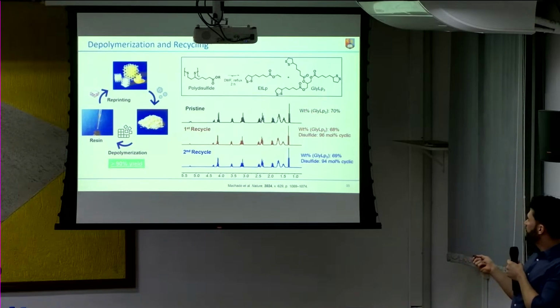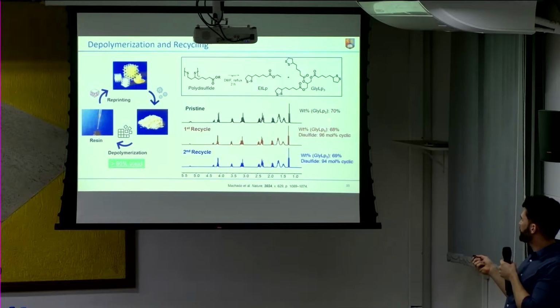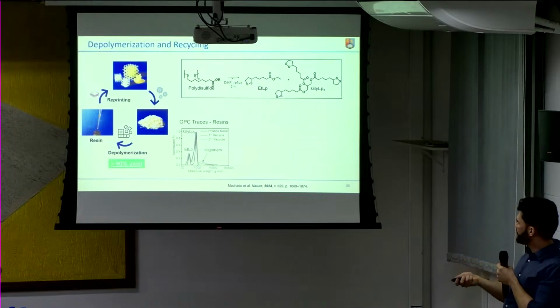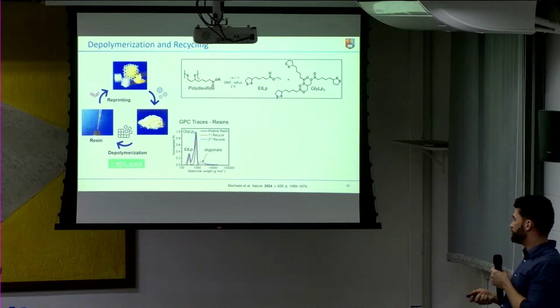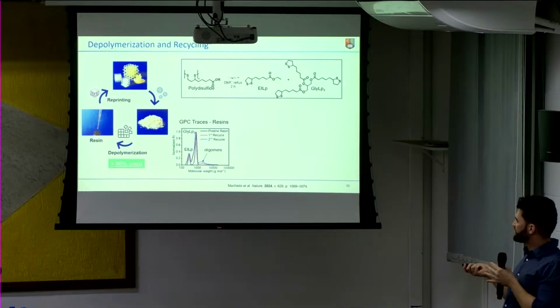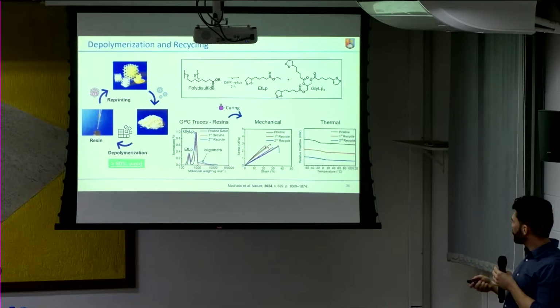So comparing the content of crosslinker, we have 70% for the pristine, 68 and 69 for the recycles, and the cyclic disulfide is recovered by 96% and 94% respectively. So we have 96% of this in the first recycle and 94% of this in the second recycle, which means that we still have some oligomers that we can see by the GPC traces. So even though we have the 4 or 5% of oligomers, we are able to recure it, and we get thermomechanical properties very similar to pristine.